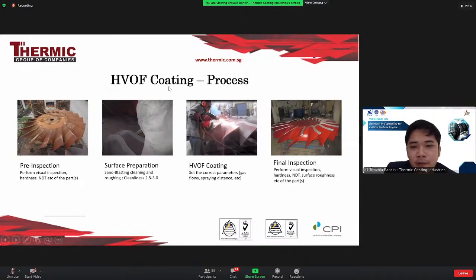Okay, this is the HVOF coating process, in brief. First, we do pre-inspection. This is a turbine blade from a coal-fired boiler. The function is to extract the dust from the boiler, and we can see the blade is almost worn, very damaged. First, we perform visual inspection, and then hardness, non-destructive tests, etc. of the parts.